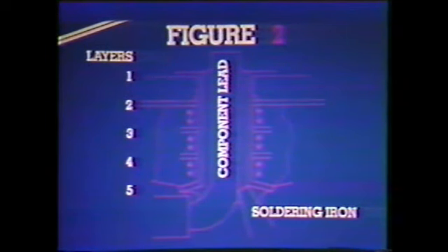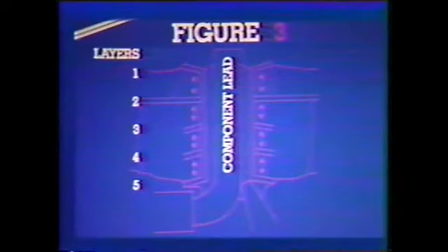As temperature increases, layer 2 acts like a heat sink and proper heat transfer is reduced through the length of the hole. Here's a look at the hole when excess heat is applied, using conventional methods. Sufficient heat transfer is achieved, but between layers 2 and 5, a tremendous amount of excess heat causes melting, burning, crazing, delamination, measling, and expansion.